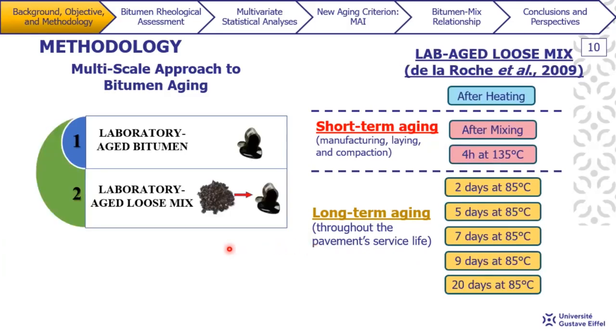So on an asphalt mix scale, we have bitumen recovered from loose mix that were aged in the laboratory. So in this case, I used the RILEM protocol that is described in De La Roche and coworkers. So here we have the bitumen that was, after being heated, like minutes before the mixing, we extract the sample. And then for short-term aging, we have the bitumen that was recovered right after the mixing, and after 4 hours at 135 degrees Celsius. And for long-term aging, we have our mix that was aged. In this case, it was loose mix, and they were aged for 2, 5, 7, 9, all the way to 20 days at 85 degrees Celsius.